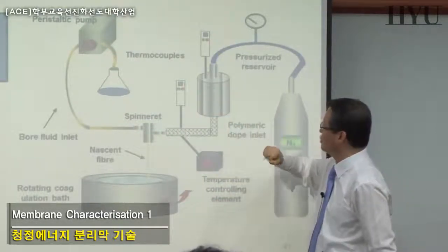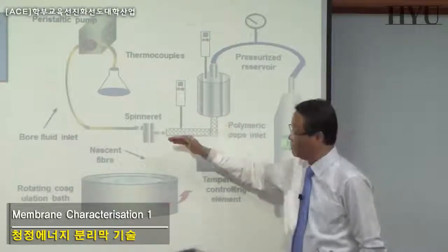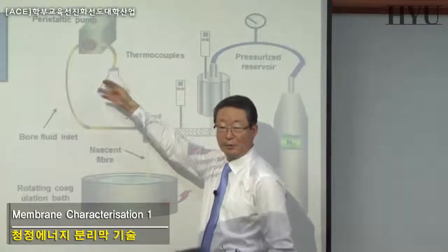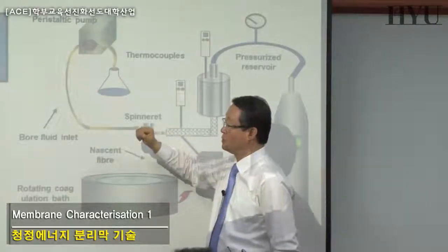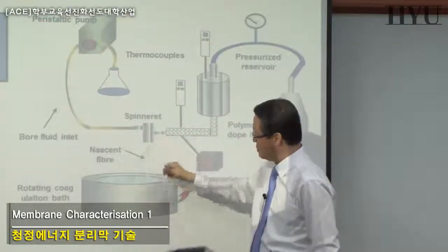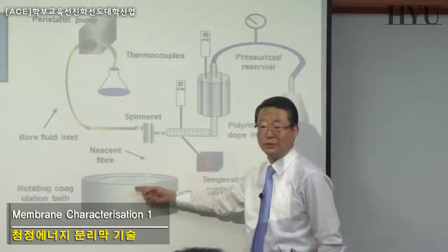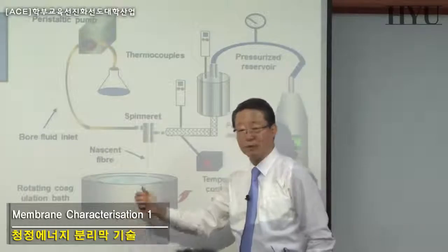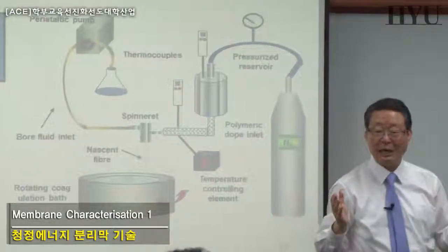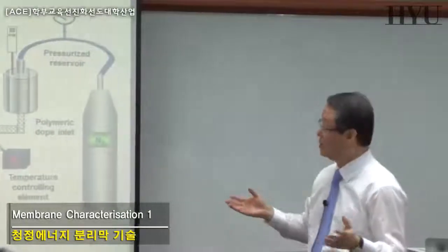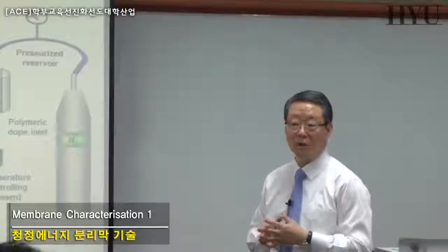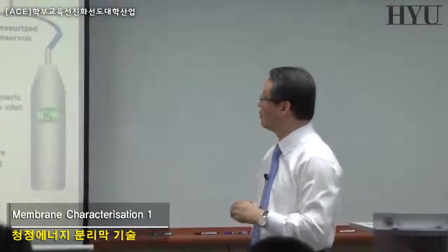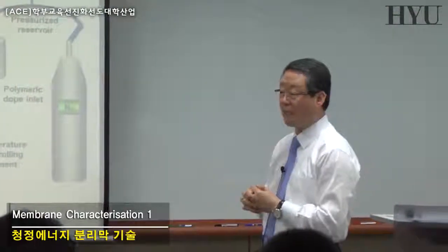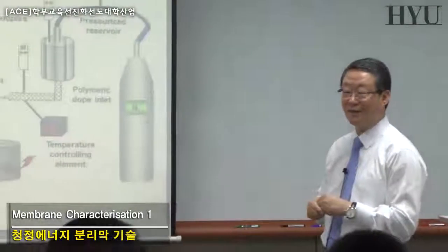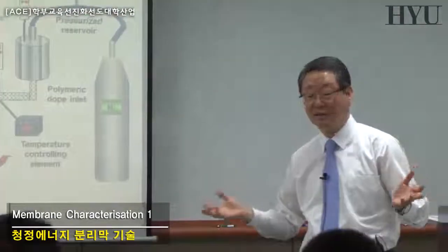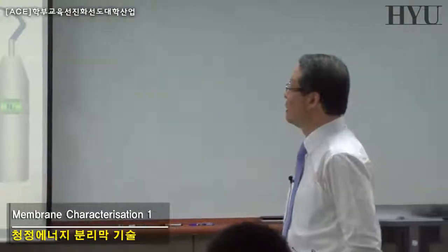Temperature of your dope solution, speed of your fluid coming in, temperature of your bore, composition of your bore, of course composition of the doped solution, air gap distance, temperature of your coagulation bath, composition of your coagulation bath, speed of your take-up roll. About 9 to 10 variables, parameters control the morphology of your fiber formation. Right? So although it looks very simple, it's an art. They say it's an art, not a science, in making this hollow fiber.